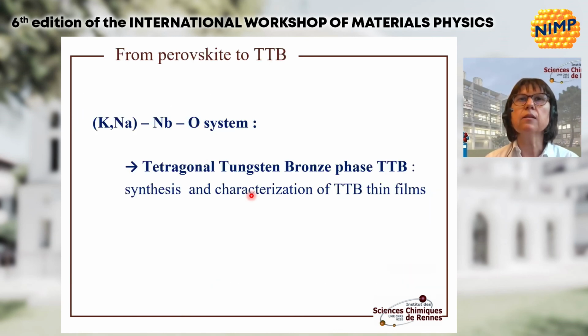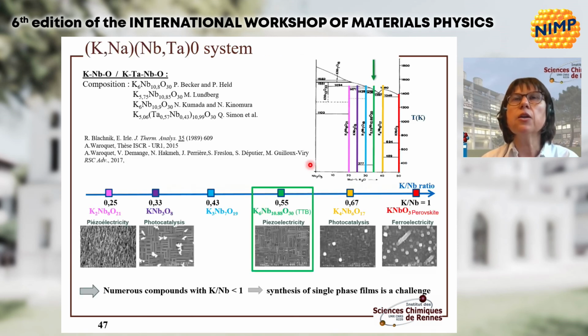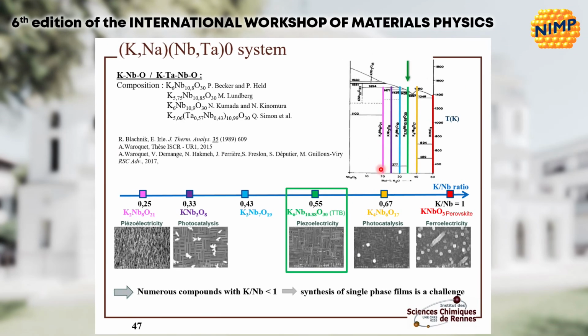So we have seen that with this perovskite KNN, it has been possible to obtain controlled growth and a device. Now what about the TTB? In the phase diagram of potassium sodium niobate, here you can see the potassium niobium oxide phase diagram. We can see that there are many phases, especially many phases with potassium over niobium ratio below 1. And one phase looks of interest.